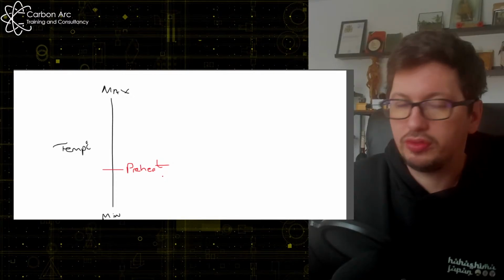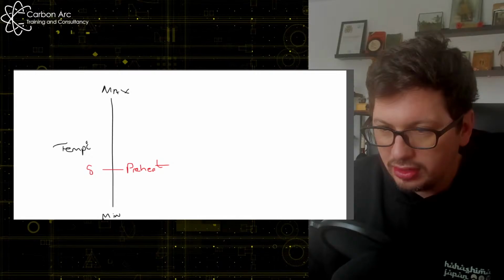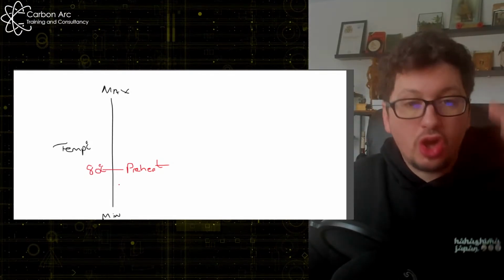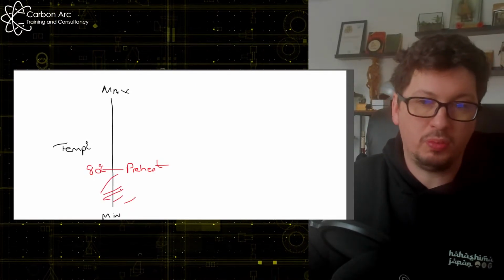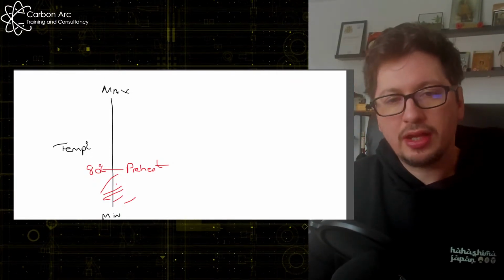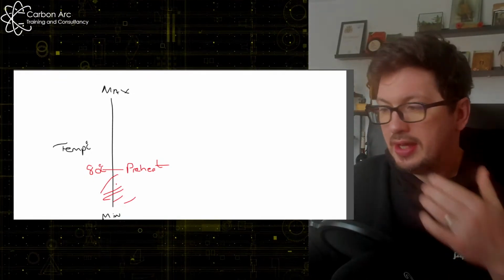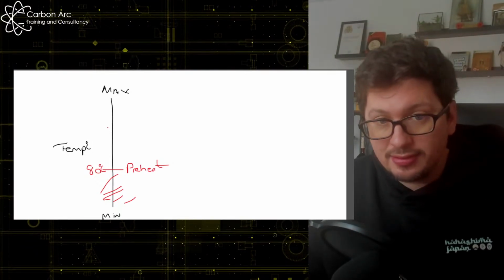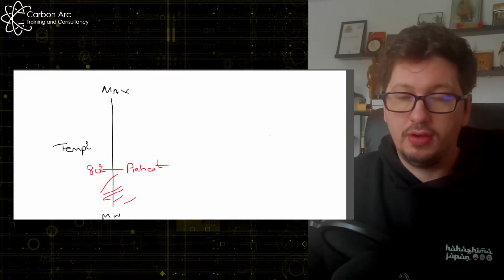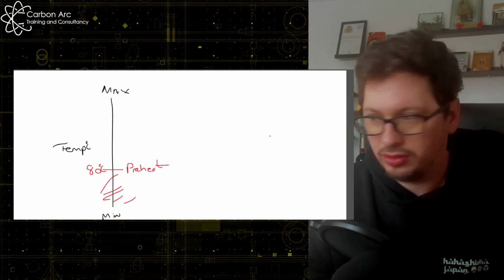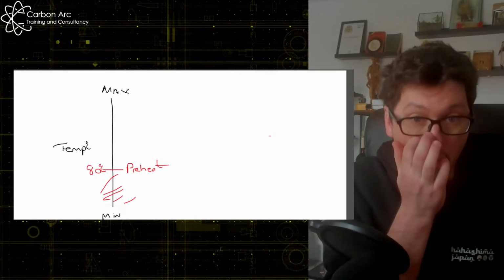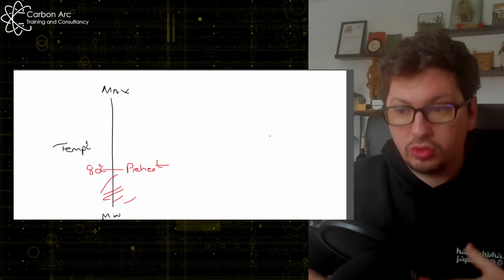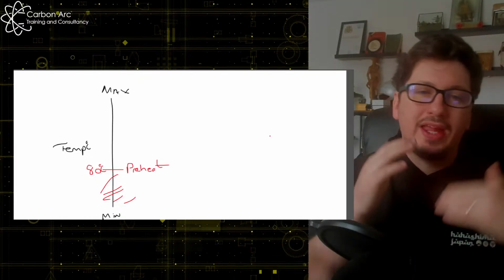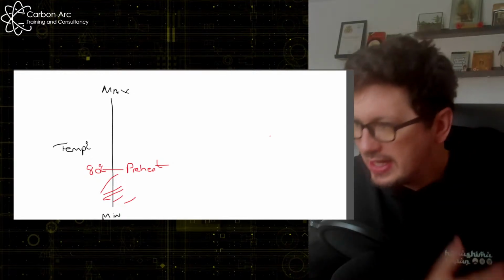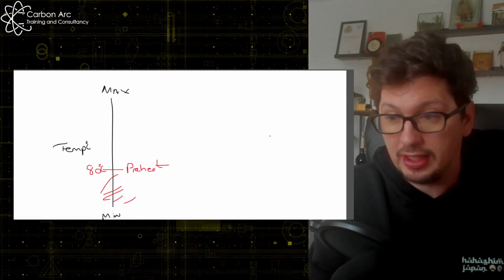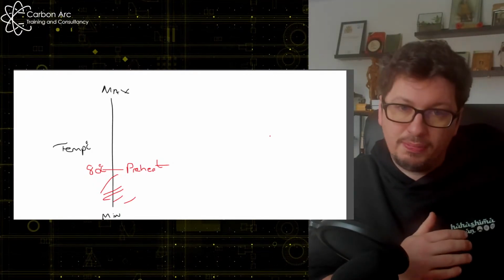So let's just say our preheat is going to be 80 degrees. So there's our temperature that we can't weld beneath. If we're below 80 degrees, we're not allowed to weld. So that gets us started. That's going to make sure we don't have too fast a cooling rate. Now what we have to do is work out the maximum temperature. In reality, we've got a weld arc at 6,000 degrees, materials melting at 1,500 degrees. So it's hot. But when we stop welding and we go to restart, we need to be below a temperature. That makes sure we're not just cooking our plate and constantly making it hotter and hotter, which would affect the toughness values. So preheat is affecting hardness, interpass is affecting toughness, really.